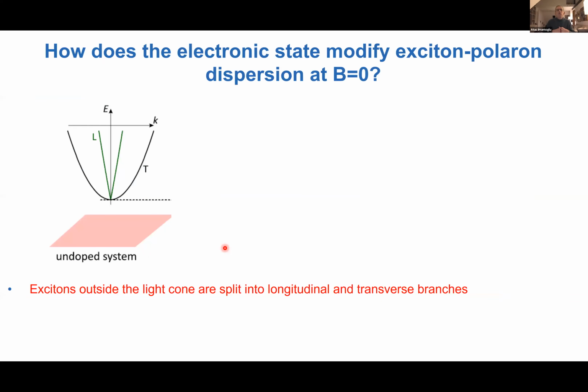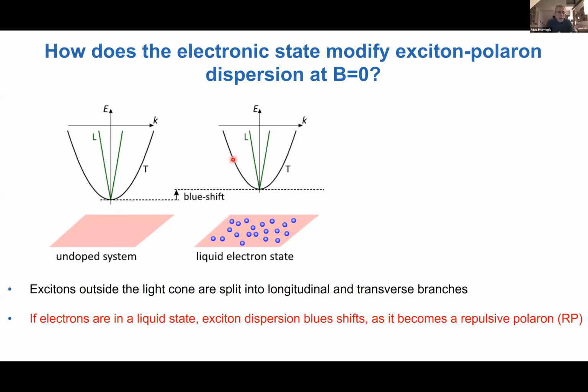Okay, so now let me go back to zero field, and let's discuss how the electronic state can generically modify the exciton polaron dispersion. Now I'm drawing the exciton dispersion with this additional twist, which is the fact that electron-hole exchange interactions also result in transverse and longitudinal excitons at high momenta. These are outside the light cone, so I will not dwell too much on it unless somebody is interested. But basically, we observe what happens at the bottom of this dispersion relation. And this is the undoped system. If you put in electrons, what we have seen is that there is a blue shift: due to the polaron formation, repulsive polaron formation, the exciton energy is blue shifted. Okay, so this is what we expect if we have a liquid state.